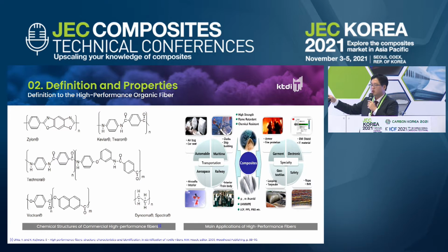So when we exclude Dyneema, all of those fibers look strong, right? They look very strong. And because of these structures, they tend to be strong, and they are flame resistant, heat resistant. But as we can see, when these types of structures are close to flame, they won't be able to survive. If it looks like that, the structure, then they are weak. They cannot be exposed to sunlight for a long time, and the tensile strength will be weakened. And in order to overcome these issues, a lot of research is being done at the academia level.